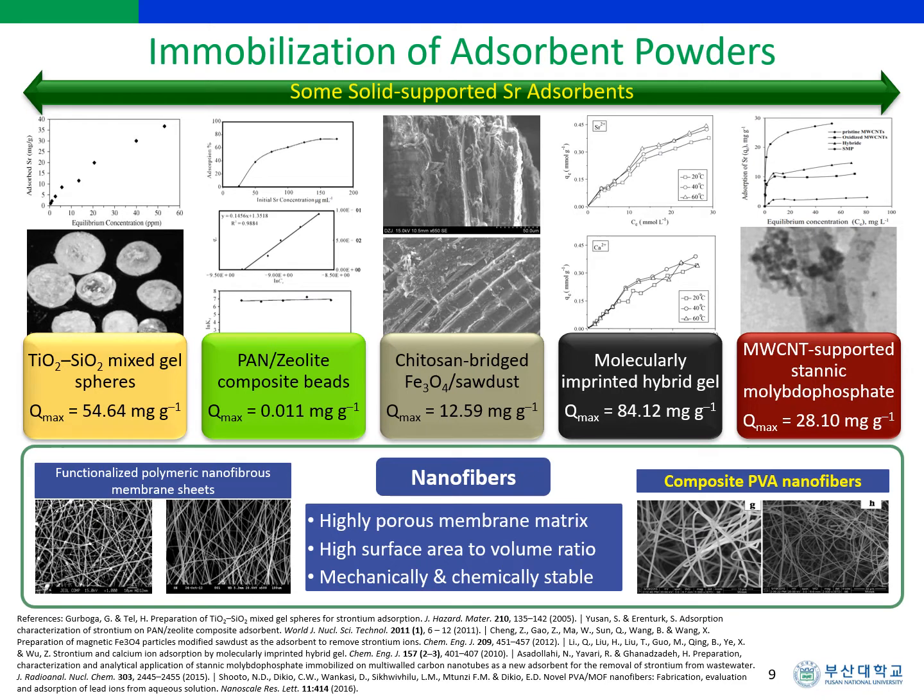Here are some examples of powdered strontium adsorbents which were immobilized in different solid supports. The researchers were successful in immobilizing the strontium adsorbent powders. However, the composite adsorbents exhibited relatively low adsorption performance in terms of strontium adsorption capacities. If you would see, the strontium adsorption capacities of these solid supported strontium adsorbents were below 100 mg per gram.